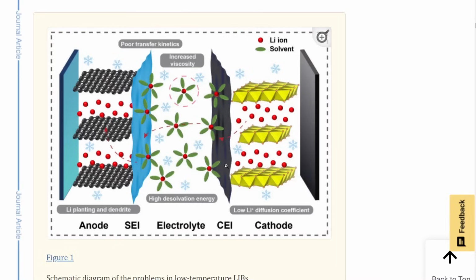And at low temperatures, the lithium ions have a hard time diffusing out of the matrix they're in, and they have a hard time solvating in the solvent. Then they have a hard time getting in between the graphite layers, and sometimes they cause plating. They form a surface plating of pure lithium right on the anode, which can make you permanently lose capacity. And if they form dendrites and pierce the separator, they can cause an internal short, and that just kills the battery.